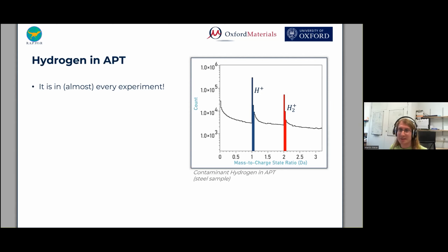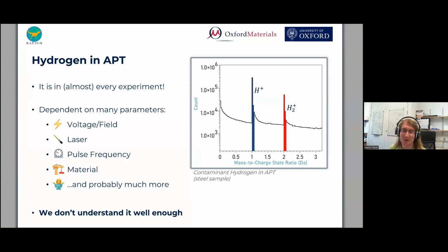And whilst this looks fairly simple, it's actually a surprisingly complex phenomenon. It depends on pretty much all of the parameters that we have at our disposal in APT. So there are dependencies on the voltage or the electric field, the laser if you're using it, the pulse frequency, the material, and that's especially a problem if you have a strong hydride former like zirconium, and probably even many more parameters that we have not even discovered yet, or that we do not have control over.